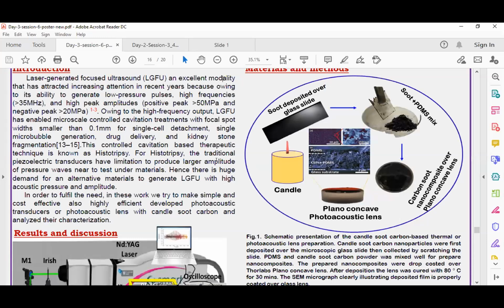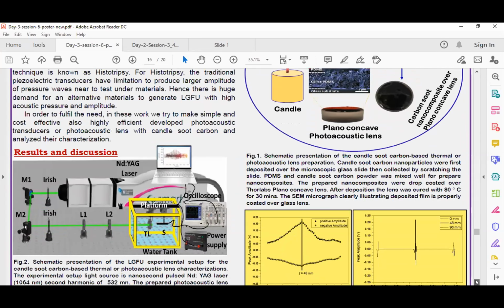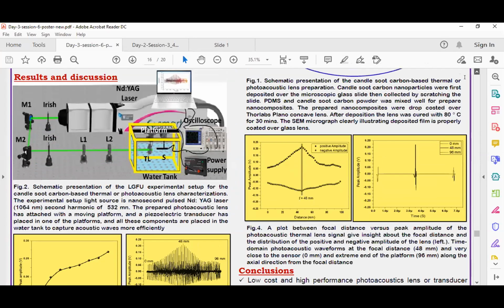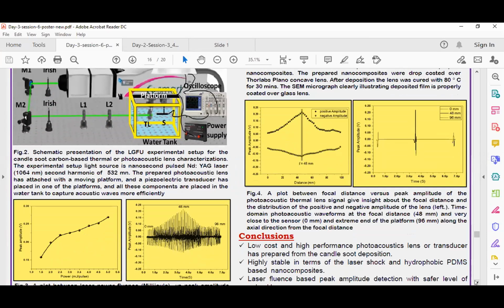In this work, we developed a carbon nanoform from candle soot, deposited over a glass slide and collected. After that, it was mixed with PDMS. That mixture is a nanocomposite placed over a commercially available plano-concave lens. I used a 2.5 centimeter focal length plano-concave lens. I used an Nd:YAG laser at 532 nanometers to pump the photoacoustic lens, and we developed a photoacoustic sensor with PVDF, polyvinylidene fluoride material, connected to an oscilloscope and also controlled with the software's moving platform. At each step, I moved 1 millimeter and checked the focal length.